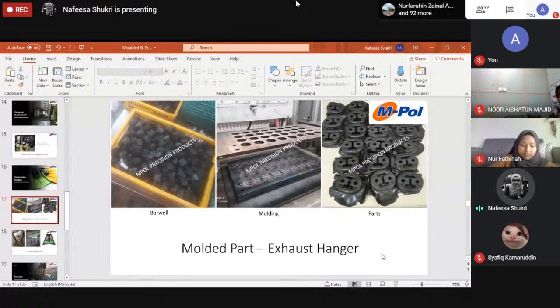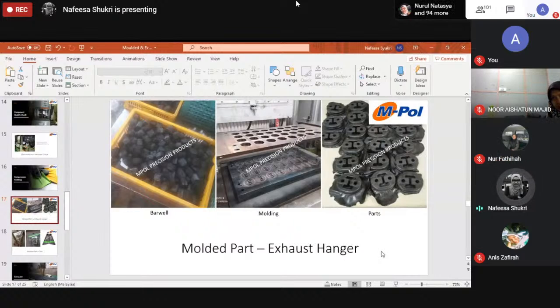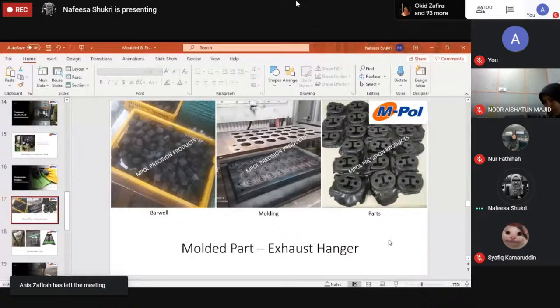So for compression moldings, the bowl size and bowl shape are very important in order to prevent short mold, and also air trap. We can do the rubber strip, stack them together and put them in the molding, but it's not advisable as it will trap air in between the rubber stacking. So it is most optimum, or most suitable, to use a solid bowl, depending on actual product size, compared to rubber strips we stack together, in order to prevent short mold and also rubber air trap.